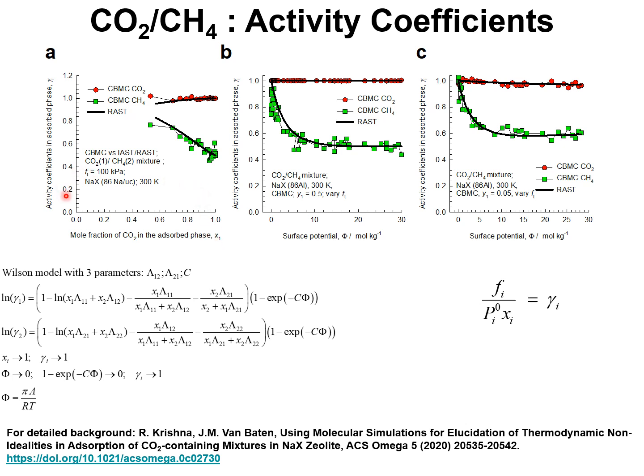As the mole fraction of CO2 in the adsorbed phase approaches unity, the activity coefficient should also approach unity. The mole fraction of CO2 in the adsorbed phase mixture is unity at this point here, and the experimental data, or in this case the simulation data, when extrapolated, should also approach unity.